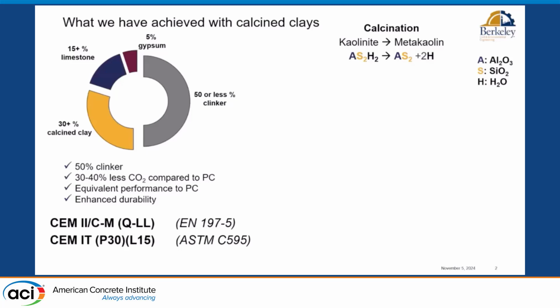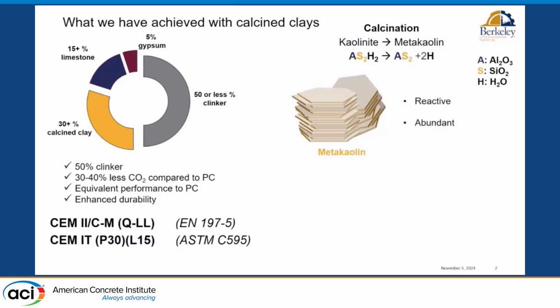The magic of the process is that we use this material called calcined clay, and the reactive component inside calcined clay, or at least the most common and most reactive of them, is metakaolin. That's a metastable amorphous aluminosilicate, and by calcination we obtain it basically by removing structural water from kaolinite, which is a crystalline material that occurs in nature, and forming this phase which is amorphous and that we call metakaolin. And the advantage of metakaolin is that it's very reactive. It's, I would say, the most reactive SCM that we have at scale to be used in cement, and it's also very abundant, so the resources are very high.